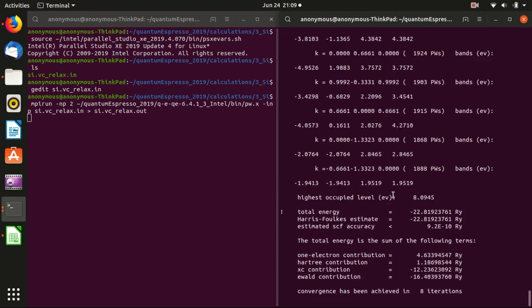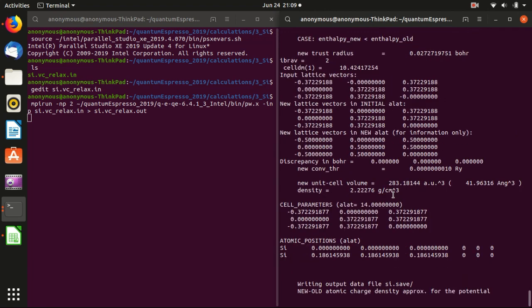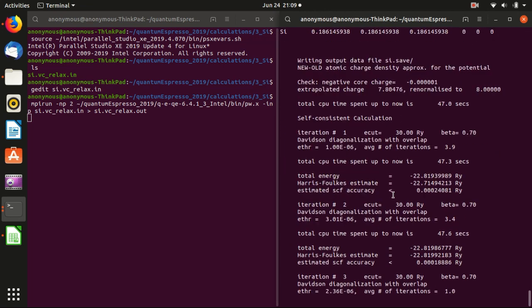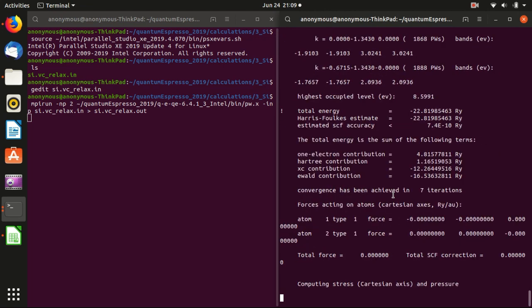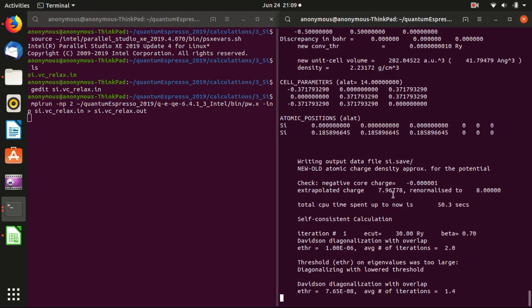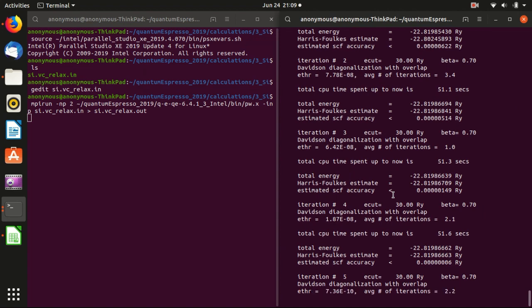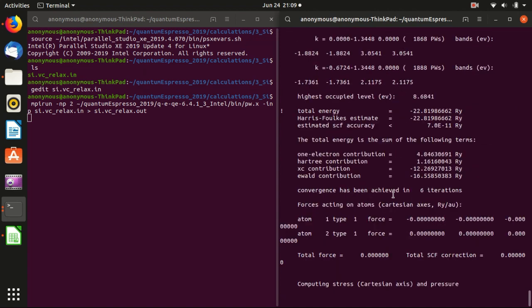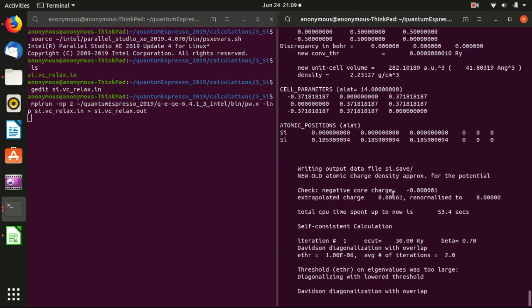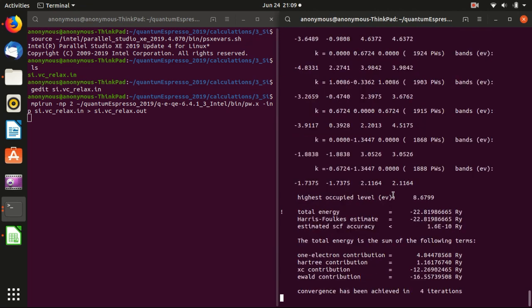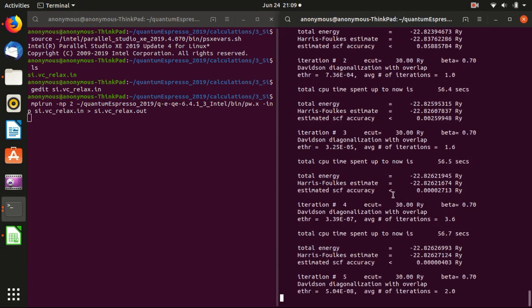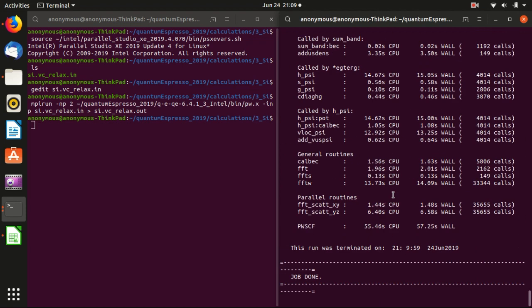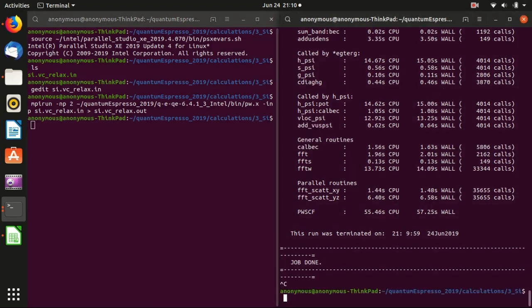So basically the process is that it calculates the force on the atoms and then it moves the atoms in one step and then calculates the force again. And then moves the atom again and calculates the force again until the force is smaller than a threshold and change in the energy is smaller than some threshold and it finds its final position. So now it's done.